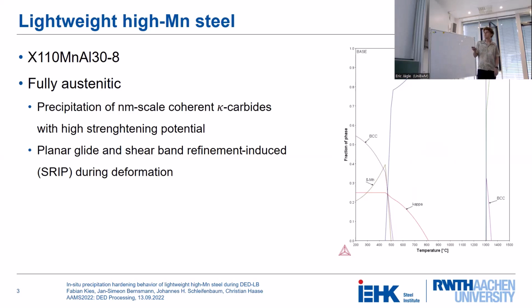And if we take a look at some CALPHAD calculation, you can see here that it's fully austenitic above about 800 degrees C, and between 500 and let's say 750 degrees C, you have the possibility to precipitate this coherent kappa-carbide phase. As you can also see, the volume fraction is quite high, so up to 20%. And that's also usually the point where you do the heat treatment of conventionally produced lightweight high manganese steels.